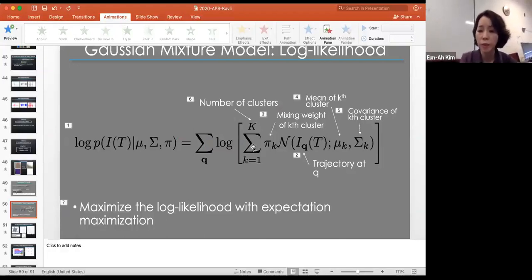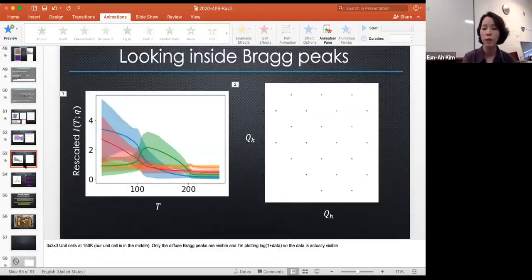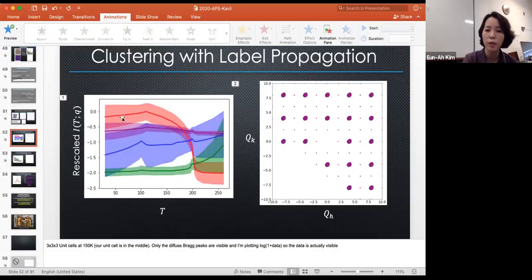And that's something that we play with, because going in, we don't know how many different kinds of behaviors there are. Typically, there would be at least 2 clusters, one being a background and one being something active. But there could be more than one behavior. At the moment, we try a couple of different cluster numbers and see whether it makes a difference and when we get a robust clustering. And what's nice about this approach is that together with the clustering, you get the variance. So when you see what are being considered as different clusters, there is this red cluster and the green cluster. Their means obviously look different, and their variance is pretty tight around that cluster. And that gives us a sense that these are meaningful clusters.